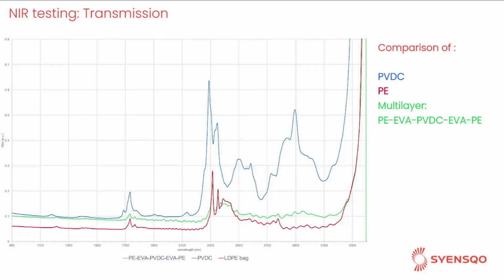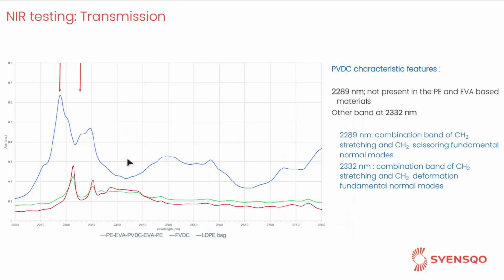And this is a survey near infrared spectrum in a very wide range of the electromagnetic region, which goes from 900 nanometers till 3,300 nanometers. Let's see in more detail a specific region to understand and see the differences and the typical features due to the presence of the chlorine atoms in the PVDC polymer. Considering the region from 2,200 nanometers till 2,800 nanometers, we can observe at least two components at 2289 and 2332, which are not present in the polyethylene and EVA-based materials.